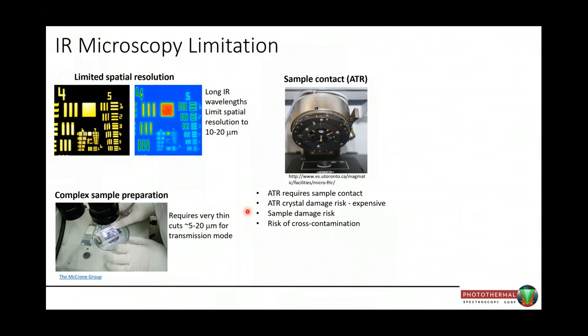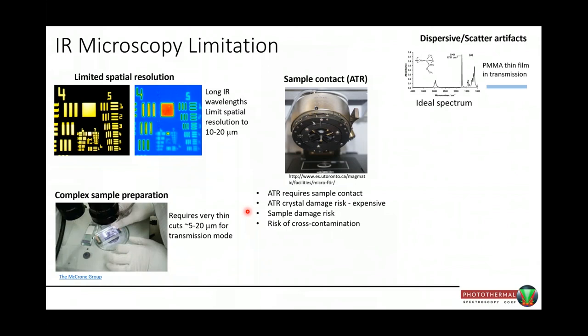The problem is, when you do that, most of the infrared light isn't reflected, and what is reflected contains lots of dispersive and scattering artifacts. The truest spectrum you can get is of a thin film transmission sample. So if you take a thin film transmission spectrum of a polymethylmethacrylate film, it comes out looking like you would expect the spectrum to look.